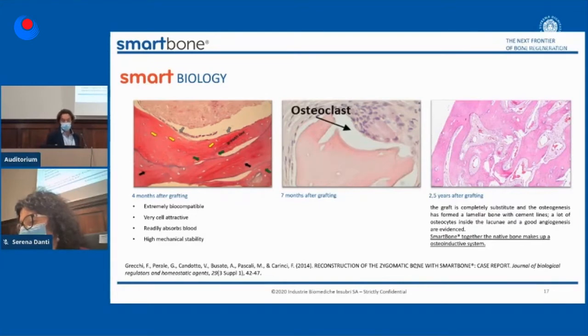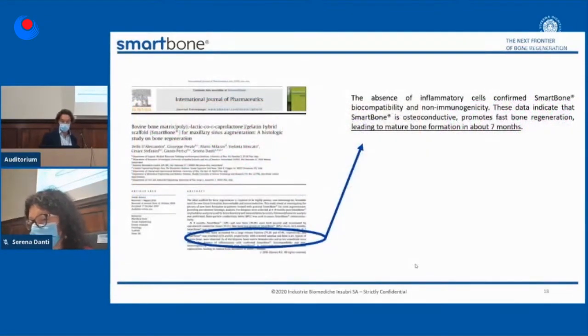After 7 months, from another biopsy, you can see that there is a large osteoclast that is still remodeling the remaining part of the bovine bone. And after 2 years and a half, we can see that there is no more evidence of the graft. We have a very well vascularized new bone formed, so the integration was really complete. We obtain a very, very good bone.